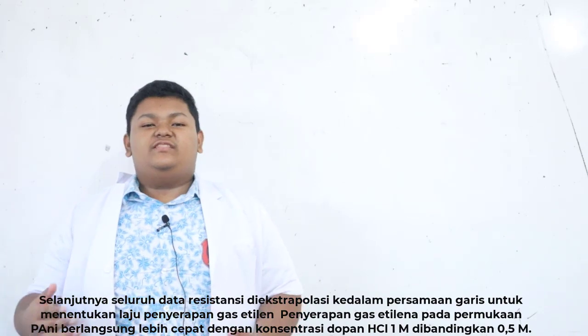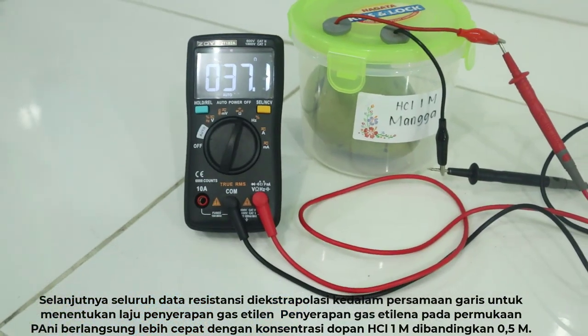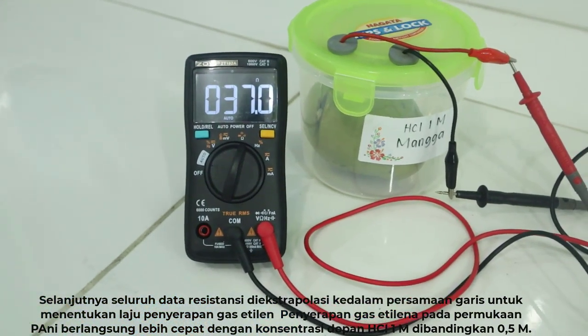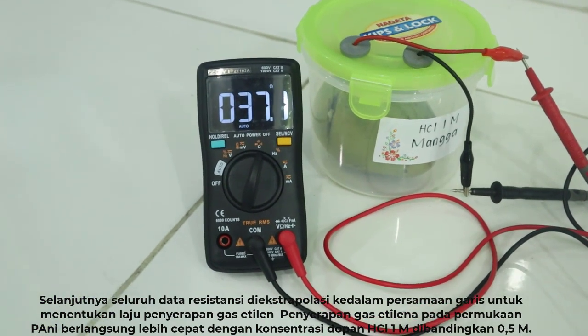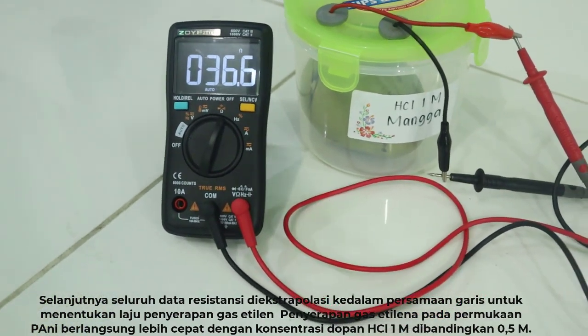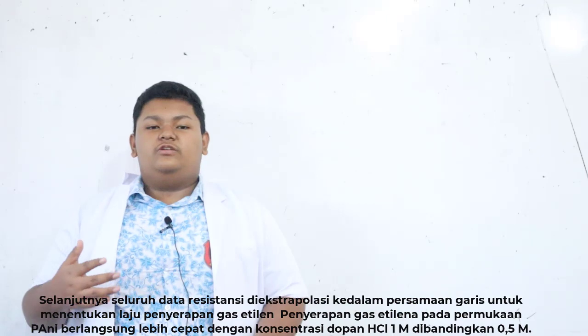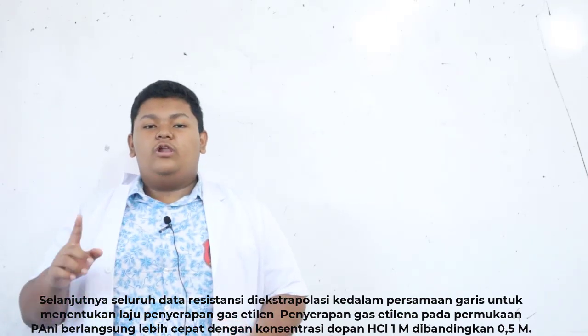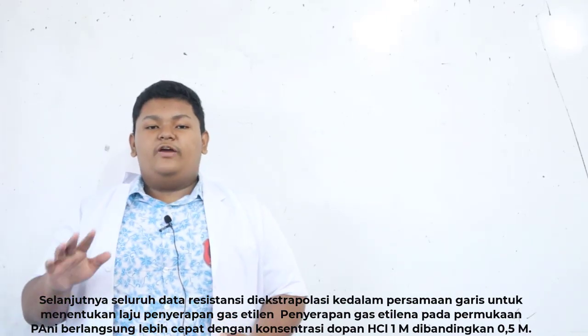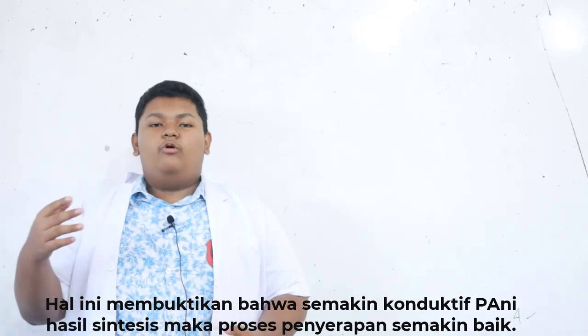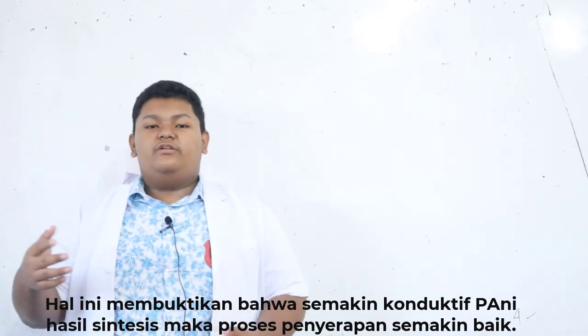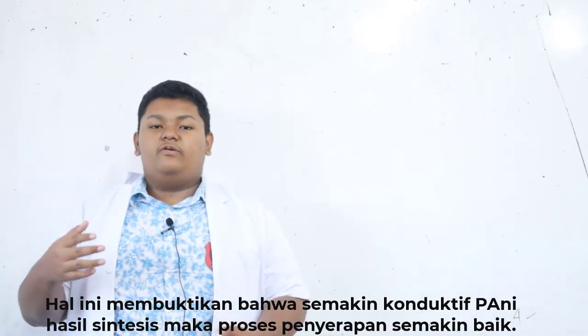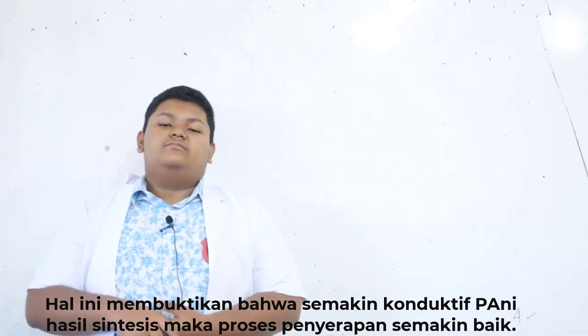Furthermore, all resistance data is extrapolated into the linear equation to determine the rate of ethylene gas absorption. The absorption of ethylene gas on the polyaniline surface rises faster with the concentration of hydrochloric acid 1 molar dopant compared to 0.5 molar. This proves that the more conductive the polyaniline that results from synthesis, the better the process of absorption.